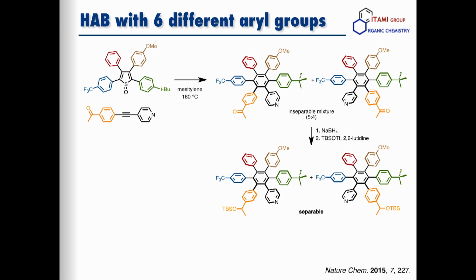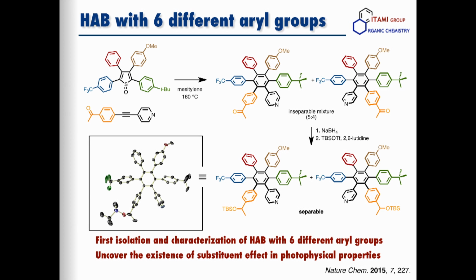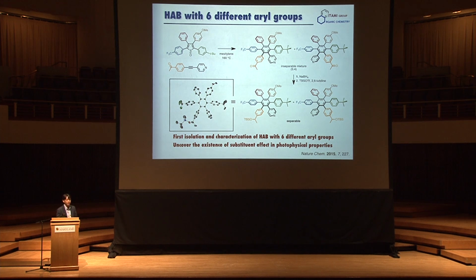But if you limit the number of isomers to 2, you can isolate them in many cases. For example, in this particular case, we did the reduction and put on the silyl group to make it easy to separate them. And the structure has been confirmed by X-ray crystal structure. Believe it or not, this simple system is the first example to isolate and characterize HAB with 6 different aryl groups, which means that HAB is largely unexplored experimentally in terms of property. So we were able to uncover the existence of a substituent effect in the photophysical property of HAB from the small library that we made. Hopefully it's going to be helpful for the future rational design of HAB.